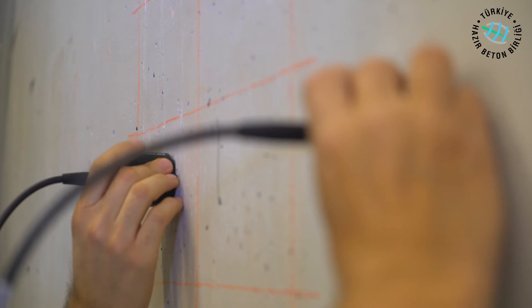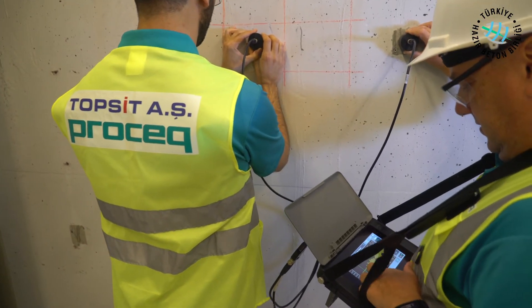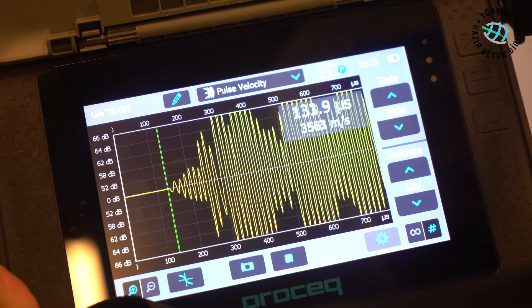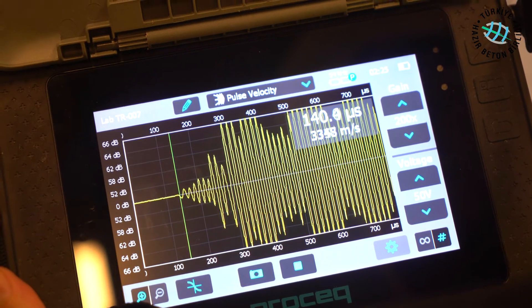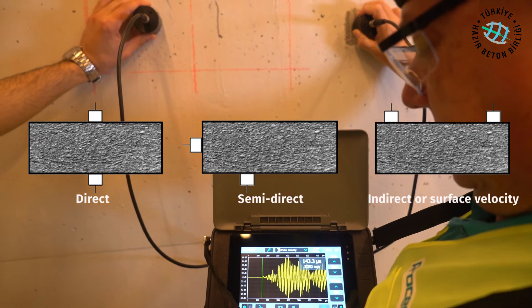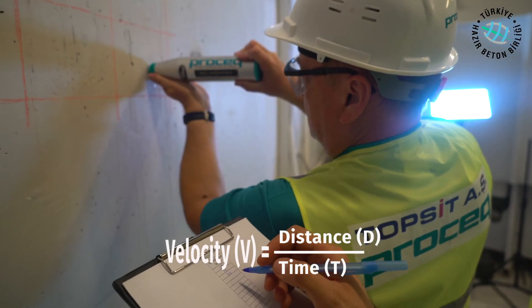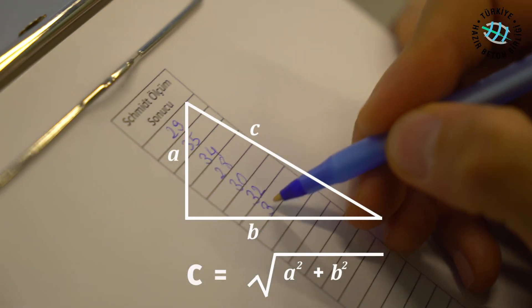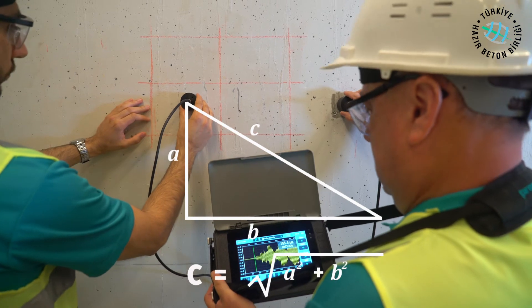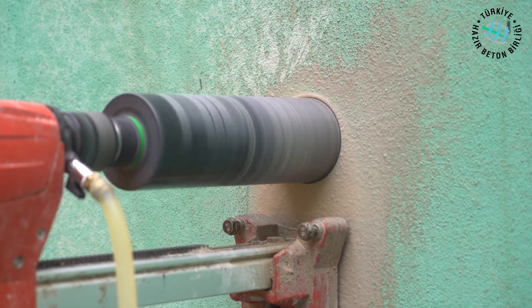Correlation of deviations arising from the hardening of concrete surfaces due to carbonation over time, and the detection of cracks and voids in the concrete, are the next stages in determining concrete strength. The ultrasonic concrete tester comes into action to determine whether the compressive strength values observed on the concrete surface are representative throughout the concrete. Measurements are made in three ways with the ultrasonic concrete tester: direct, semi-direct, and indirect or surface.